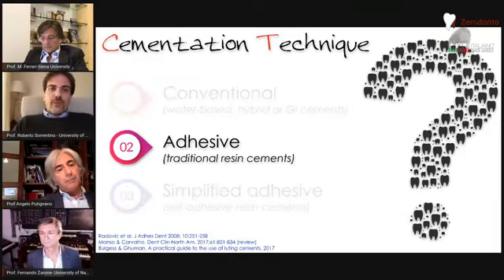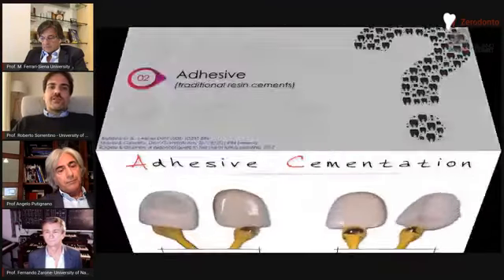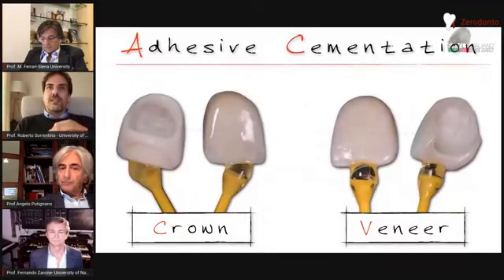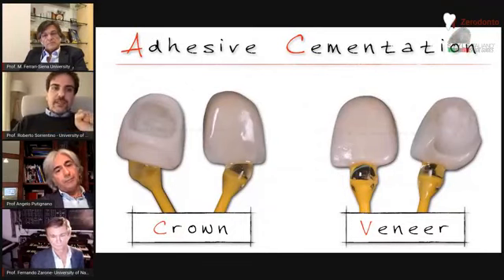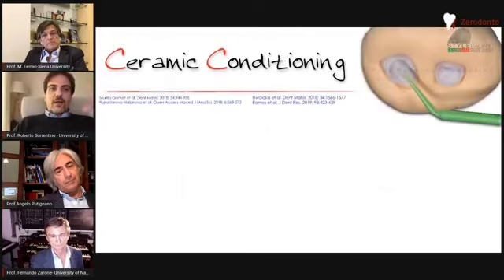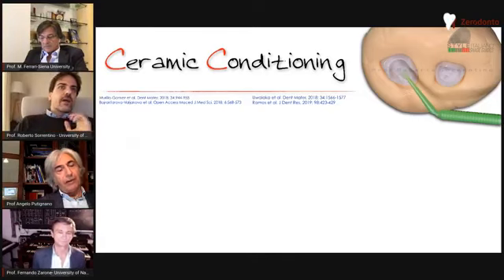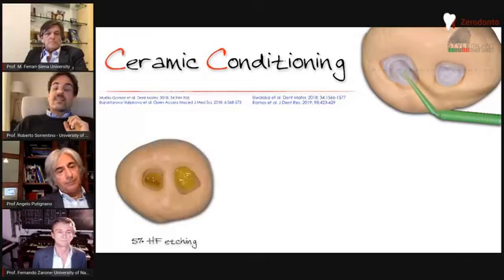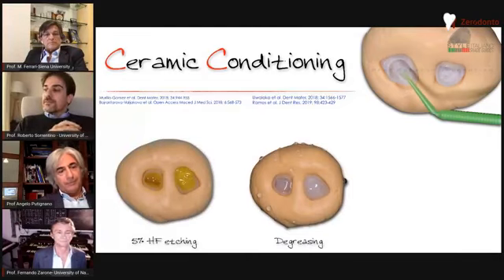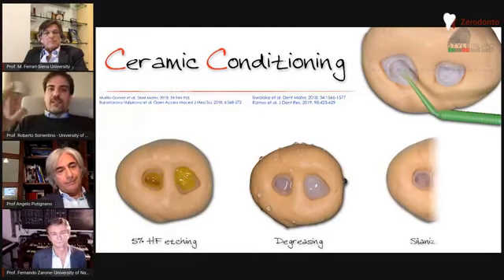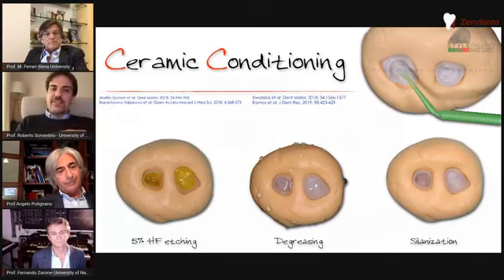And of course, as you have anticipated, it is necessary to condition the ceramic surface before proceeding to the clinical steps of cementation. And briefly, this is another very hot topic. We can summarize the lithium disilicate conditioning into 3 steps. Hydrofluoric acid etching for 20 seconds, 5%. Yes, 5%. You know that in the US they are using 9%.